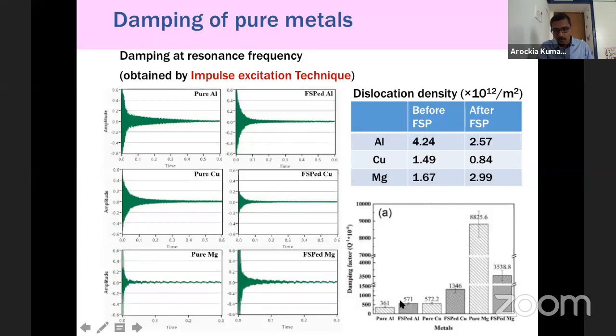The same thing I have shown here. Pure aluminium damping property is increased 1.5 times, whereas the damping property of copper is doubled, whereas the damping property of magnesium after FSP greatly decreased. This is because of how magnesium damps the vibration. The movement of dislocations has to be allowed for effective damping. But in magnesium after FSP, FSP produces a lot of dislocation tangles, and these tangles do not allow dislocation movement during any external vibration, and thereby reduce the damping property. Whereas in the other materials, it increases.